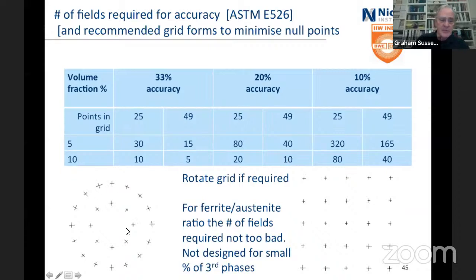Here's the grids. You can have either a circular one or that, and you can pick however many numbers you want. But if you do a lot of them, then you get better accuracy. You may have to rotate the grid just to avoid any sort of periodicity, but it's definitely not designed for small percentages of third phases. It's designed really for looking at, are you at 30 or 40 or 50 or 60%? Because by the time you get down to this, then the work gets ridiculous.